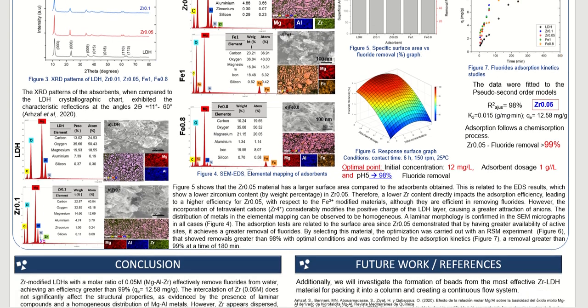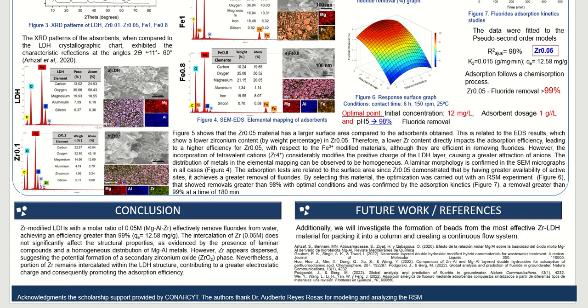Conclusions are that hydrotalcite modified with zirconium with a molar ratio of 0.05 molar effectively removes fluorides from water. However, to establish conclusions about the adsorption process, research continues with the study of isotherms, thermodynamics, and regeneration. In addition to testing with groundwater from the state of Morelos, it is also intended to investigate the formation of pellets with the material zirconium 0.05, which was the most efficient, in order to pack it in a column and study the behavior in a continuous flow system. Thank you so much for your attention.